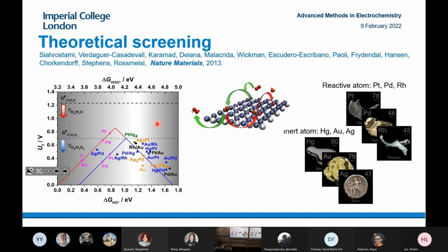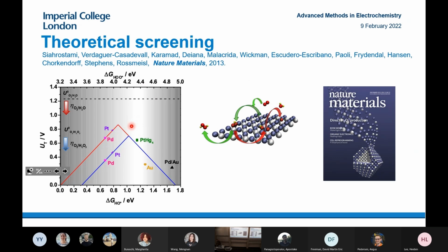Looking at different alloys, people had already tried gold alloys. We thought, why not try mercury alloys? We thought mercury is very stable electrochemically, and it's very inert. A lot of electrochemistry in the past was done on mercury alloys. So we screened a lot of catalysts. A lot of them looked promising initially, but pretty much none of them was stable. The only one that was really stable was the platinum mercury alloy.